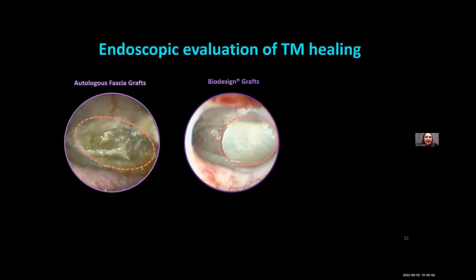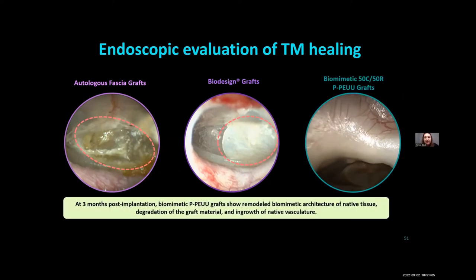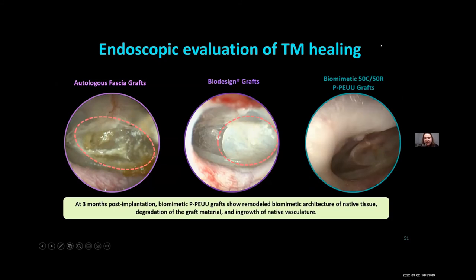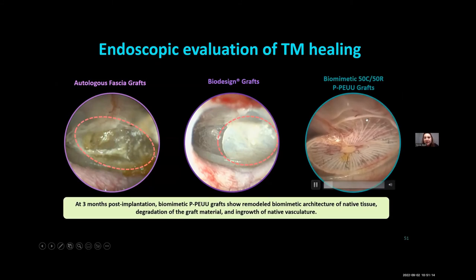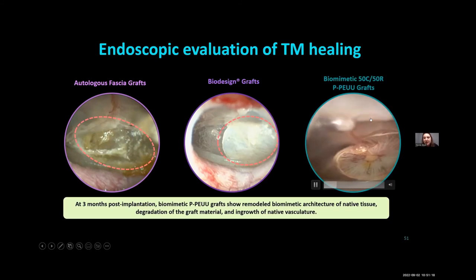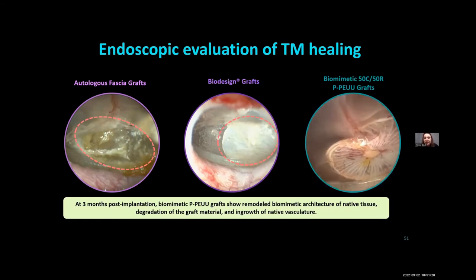And what we're able to see is that essentially after 3 months, the fascia and biodesign grafts do close the perforation, but you can see that the graft material is still there and it hasn't really remodeled into any new type of tissue. It's just sort of like a tissue bandage on that original perforation. However, in the case of the biomimetic 3D printed polyurethane grafts, you can see this graft actually integrating into the native tissue, and you can see ingrowth of native vasculature as well. So this tissue is actually reformed to look like that original print path.